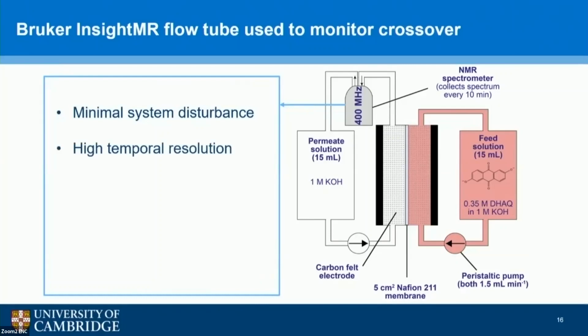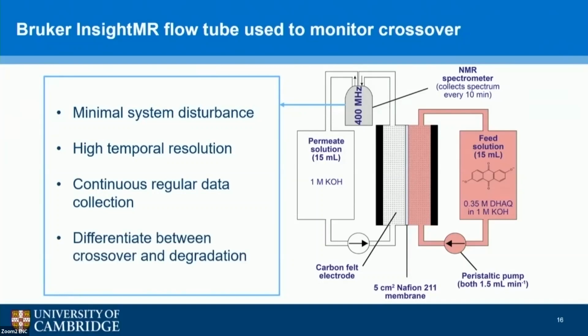We also have high temporal resolution that isn't possible with ex situ, which is particularly useful if we're looking for more transient species. Here I've taken a spectrum every 10 minutes, but we can reduce this to less than a minute if needed. Also, we have continuous regular data collection. For example, at night the department's closed, so you can't really be collecting data if you're doing this ex situ. And the excellent thing about using NMR is we can differentiate between crossover and degradation.